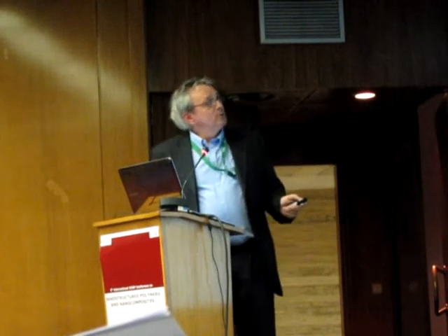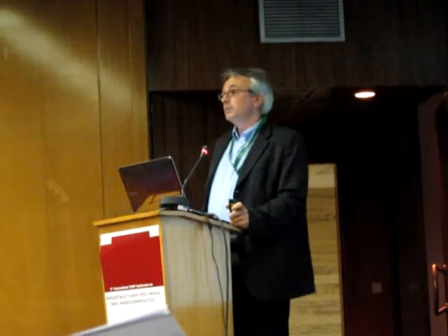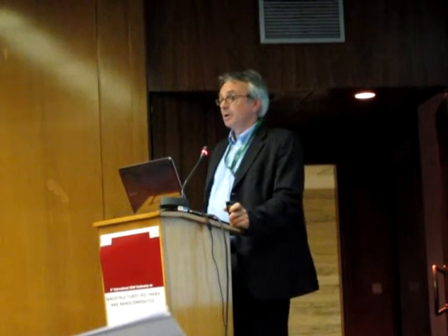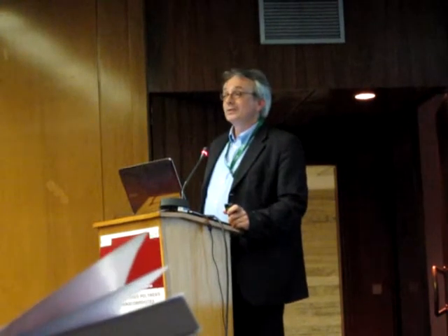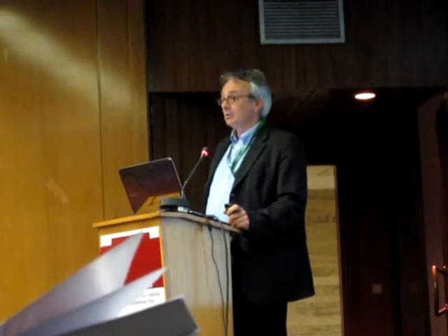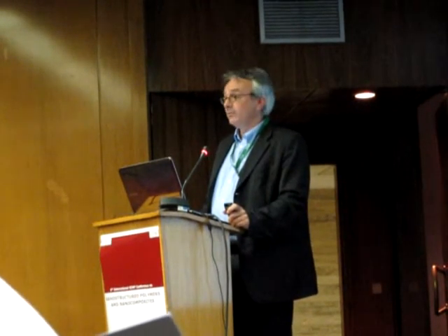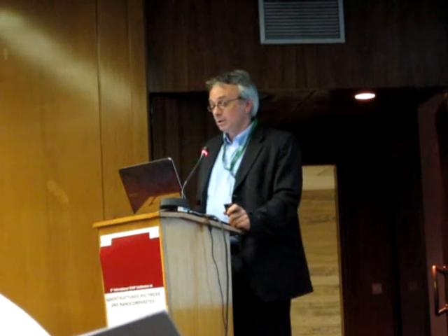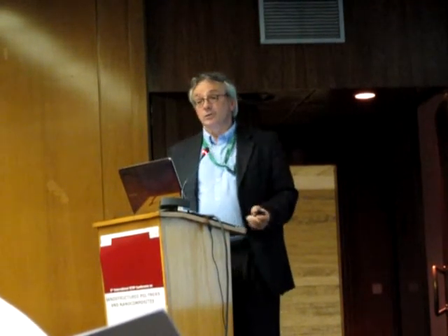So if we look at nanoparticles already preformed and put into a polymer, the problem is processing. Because if you put nanoparticles into a polymer, you will face a very difficult problem coming from the interaction between those colloidal particles, and the consequence will be a high viscosity of the system.